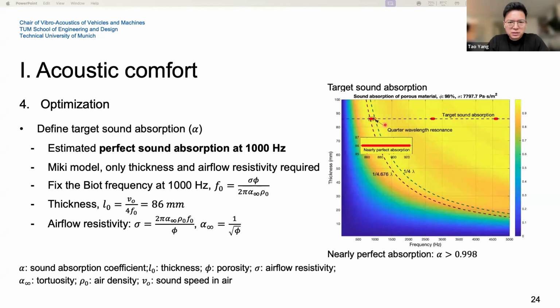It's quite interesting. We found that when I plot the graph, the nearly perfect sound absorption happened around 850 instead of 1000. It means in some cases, if the material is thick enough, it's no longer quarter wavelength resonance, but a little bit smaller. But it didn't work for material thinner than 40 millimeter.